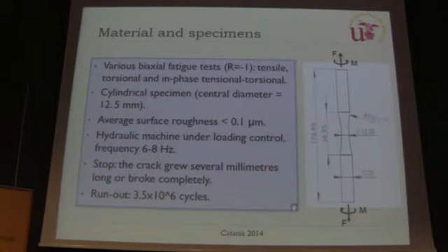About the fatigue tests, we did fully reversed tests in tension, in torsion, and in-phase tension-torsion. The specimens are cylindrical with a central diameter of 12.5 millimeters. We carefully polished the specimens, used a hydraulic machine, and the runout was 3.5 million cycles.